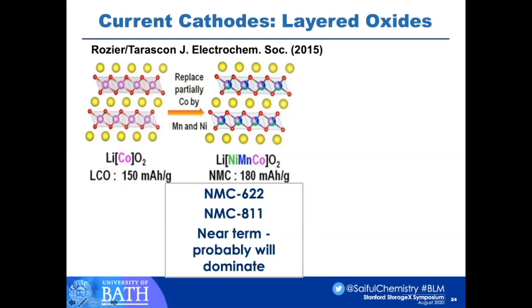As you know, the prototype material was lithium cobalt oxide. Then we went to NMC. I suppose 622 is about 180 milliampere hours per gram. NMC 811, about 200. And I think in the near term, these nickel-rich NMCs will probably dominate.